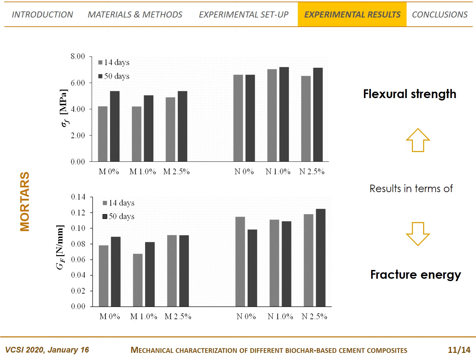As regards mortar type N, a different trend can be observed with respect to mortar type M, probably due to how biochar interacts with the type of cement and the water to cement ratio. In this case, the addition of 1% leads to an increase of flexural strength, while for 2.5% only the results at 50 days are improved. The highest percentage of addition seems the most promising in terms of fracture energy, even if the role of biochar on toughness for mortar type N is a little bit difficult to interpret, since, as can be seen, the results at 14 and 50 days curing do not follow the same trend.